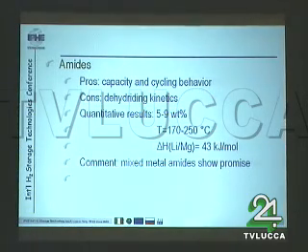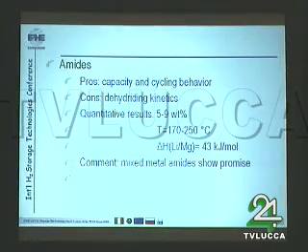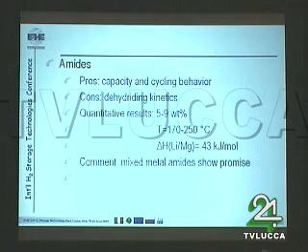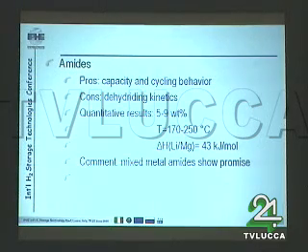Amides. The pros are capacity and cycling behavior. Cons, dehydriding kinetics. Quantitative results are promising, from 5 to 9 weight%. Temperatures are still a little bit high, between 170 and 250 degrees centigrade. Enthalpies 43 kilojoule per mole. Mixed metal amides show promise.